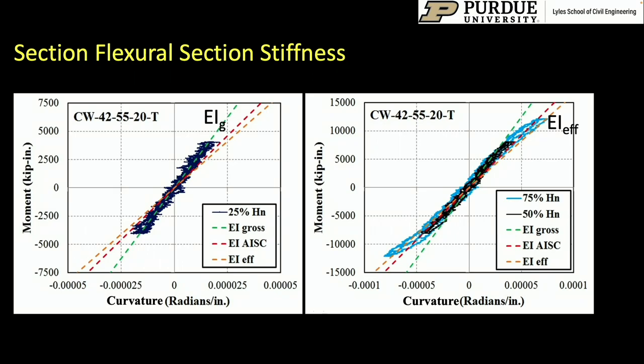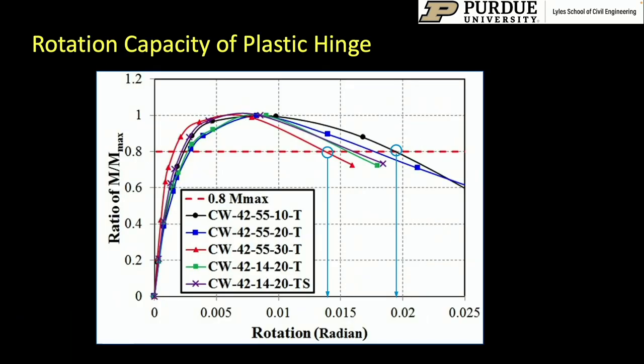Similarly, we compared the stiffnesses that we got from the experiments with the recommendations that we had provided in AISC and also the EI effective equations that you saw earlier, and we were able to verify that those recommendations for the stiffness, the equations that you saw earlier, were indeed based on experimental data. From all of this experimental research, we were also able to look at the rotation capacity, or the ductility, of this wall at the base plastic hinge.